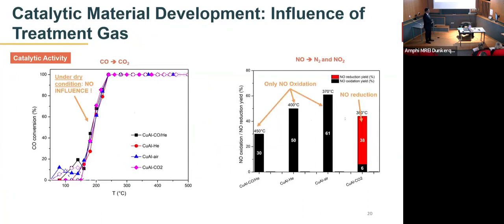So let's compare the catalytic activity or performance of the different mixed oxides. We used two different tests: one under the dry reaction condition, so without water in the reaction stream, and the other under water conditions, or the wet reaction condition. Here what you see is the dry reaction condition. Under the dry reaction condition, we don't see an appreciable difference in the CO conversion activity. In the case of the NO conversion activity, for the carbon monoxide, helium, and air treated samples, we see the formation of NO2 only, so we have a high NO oxidation yield. In the case of the CO2 treated sample, we have less NO2 formation and more NO reduction yield, which is around 38%.